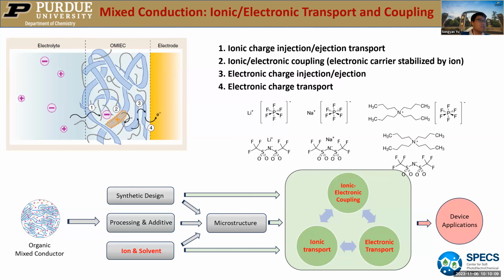Here is a brief introduction of the mixed conduction mechanism. Basically we have separate processes. We have ionic charge injection and ejection, transported from the electrode to the polymer. We have ionic and electronic coupling, meaning that the electronic charge carrier is stabilized by ions. We also have electronic charge transport within this polymer, and then we have electronic charge injection and ejection between the polymer and the electrode.